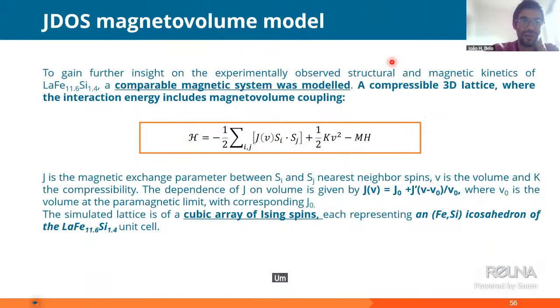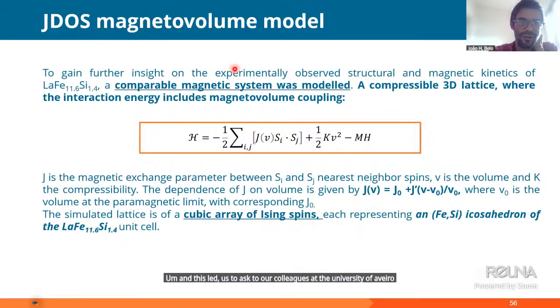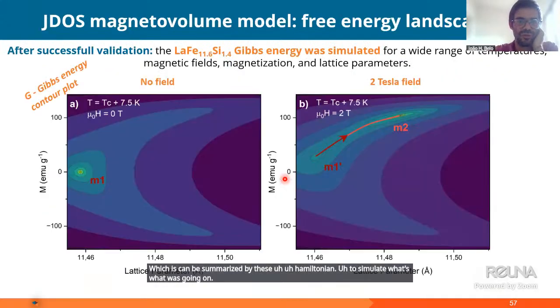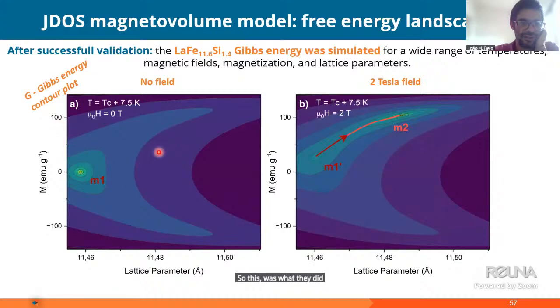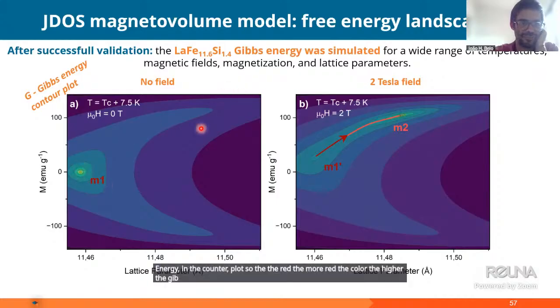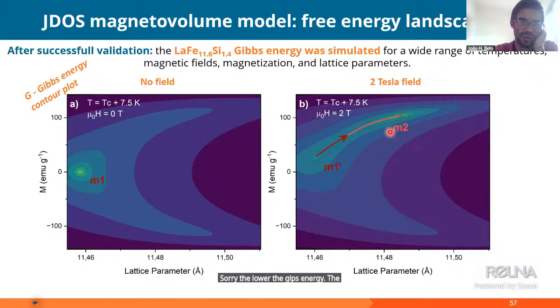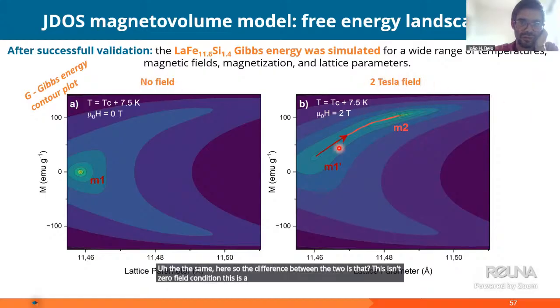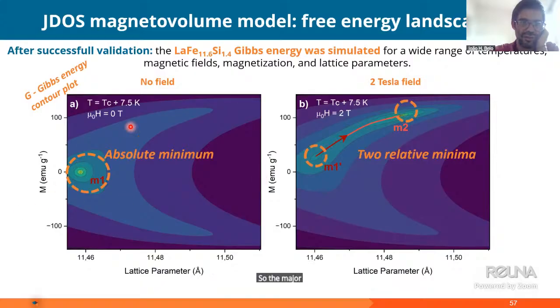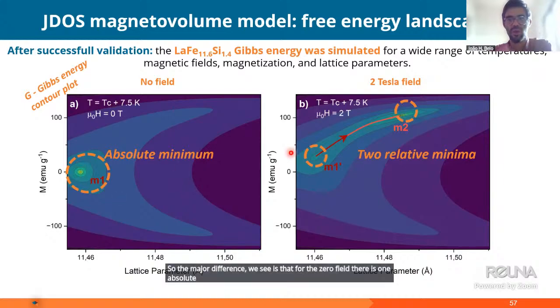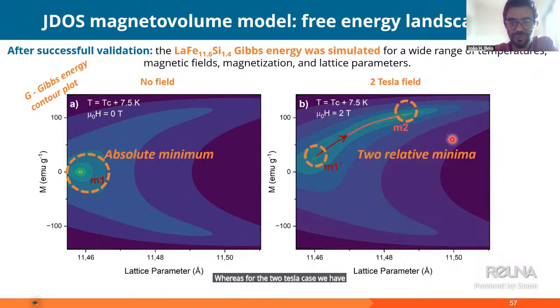And this led us to ask our colleagues at the University of Aveiro to develop a magnetovolume model, which can be summarized by this Hamiltonian, to simulate what was going on. So this was what they did. Here you see the Gibbs energy in the contour plot. So the more red the color, the lower the Gibbs energy, lower in terms of negative, I mean. The same here. The difference between the two is that this is a 0 field condition and this is a 2 Tesla field condition. So the major difference we see is that for the 0 field, there is 1 absolute minimum, whereas for the 2 Tesla case, we have 2 relative minima.